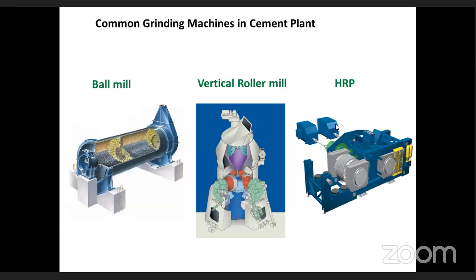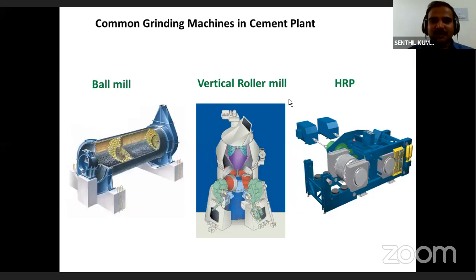Okay. So for the hydraulic roller press, when we see the wear rate on the liners, whether it is a vertical roller mill or the HRP, it will not be the same. After some time, the liner will start to rotate. The wear will be in a slightly triangular shape. Towards the center of the mill, the wear rate will be on the higher side. So what we do is we reverse the liners so that the life can be improved. Even for the rollers, it is the same. We reverse the rollers.